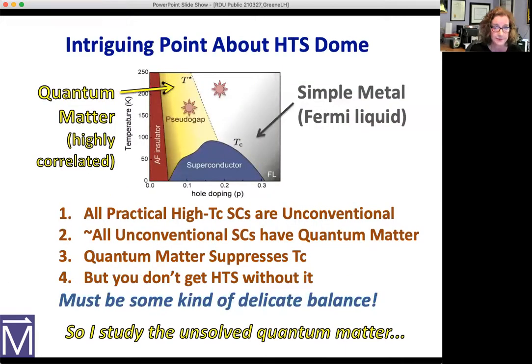Okay, so this is, I love these kind of like, they give you too much food, the food's terrible, but they don't give you enough, okay? Interesting point about the high temperature superconducting dome. As I mentioned, on the right side, it's a simple metal, below the dome, it's a superconductor. Thing about a dome is that it's highest in the center and it's lower on the sides, which means on the right side, if it's weakly correlated, it's a simple metal, TC is driven down. But as the correlations increase across here, TC goes up, and then if you keep increasing the correlation, it goes down again. In fact, we know on this side, these strange kinds of phases actually steal spectral weight from the superconductor. So, even though these correlations push down the superconductivity, you don't get high TC without it.